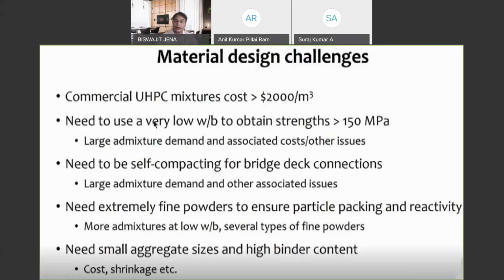So you have such a vast size distribution, and the other challenge is to make sure that you have enough particles in all these size ranges to fill the pores really well, and using a lot of admixtures to make sure that it flows really well, and you can pour your concrete into all these very tiny areas. Those are the challenges for us to design in ultra high performance concrete.